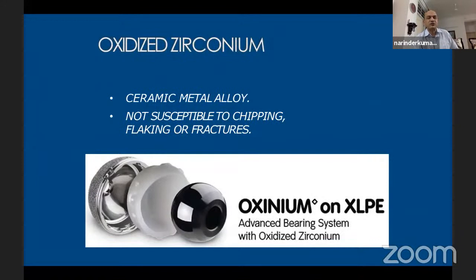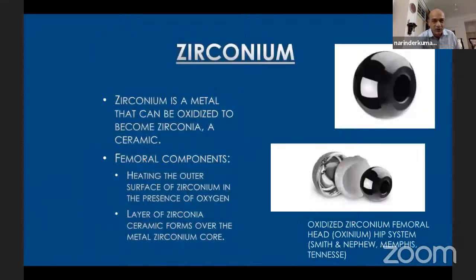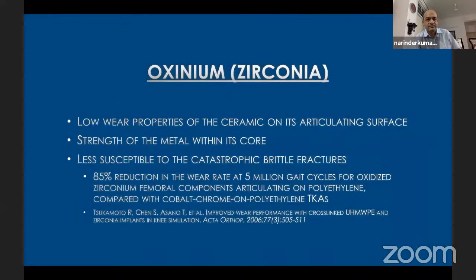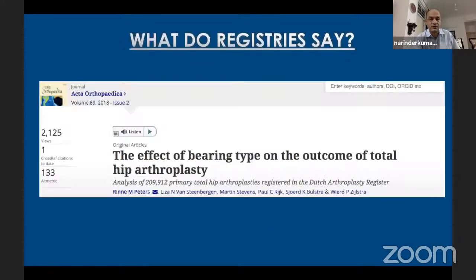And the final option, the oxidized zirconium, the ceramic metal alloy, which is patented by Smith and Nephew, so I will not be encouraging about it too much. But it is metal that can be oxidized, which becomes zirconia on the surface, where you heat the outer surface, which now becomes the patented name Oxinium, the oxidized zirconium femoral head. It has similar properties to ceramic, low wear properties, but the advantage of the strength of the metal within its core. So it becomes less susceptible to the brittle fractures which ceramics were susceptible to.